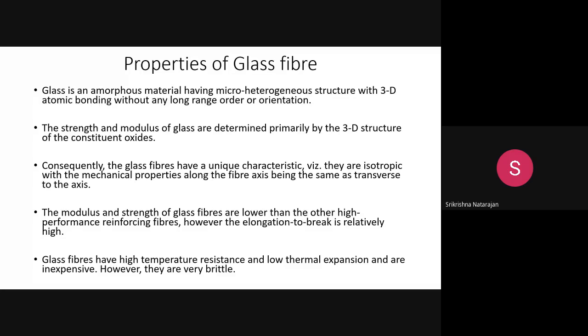And an advantage is that it has high temperature resistance. Okay, because the melting point of silica itself is around 1713 degrees, and you have brought them to 700 degrees centigrade. So this fiber has high temperature resistance and low thermal expansion. If you compare it with metals, they normally have high thermal expansion. If you apply some temperature, it will expand. So the coefficient of thermal expansion will be higher in metal, whereas for glass fiber, if you apply temperature, it will not expand that much. It has low thermal expansion.